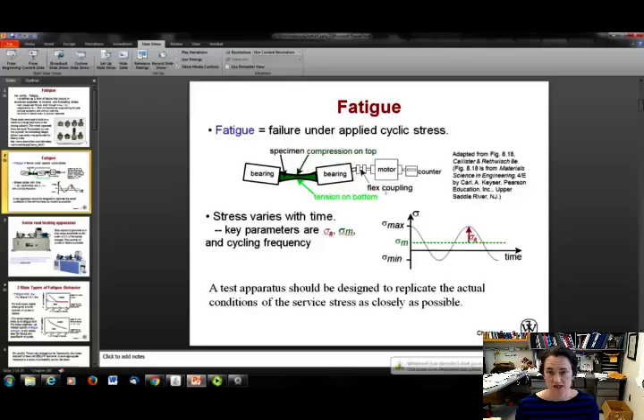Basically, what they do is they subject it to this sort of beautiful sinusoidal stress. Now, in reality, in service, the stress might not be that beautiful and sinusoidal. It might be much more erratic, but machines do the best they can to simulate that stress. And what they do is they set this stress parameter here. You can change the mean or average stress, and you can change the stress amplitude. You can change the frequency of the oscillations of the stress, and then you just run it to failure. You wait until the part breaks, and you do that for multiple scenarios on the same type of material so that you can get a feel for how that part will perform under a cyclic applied stress.